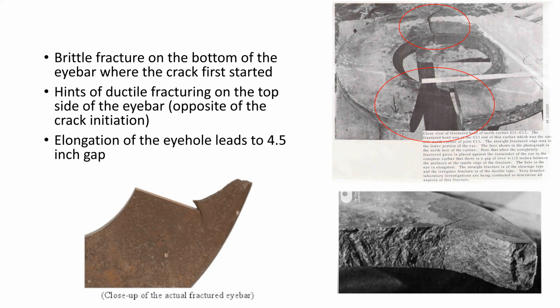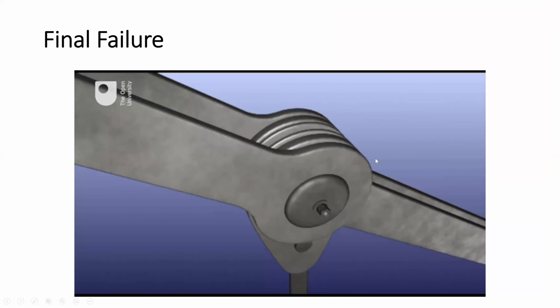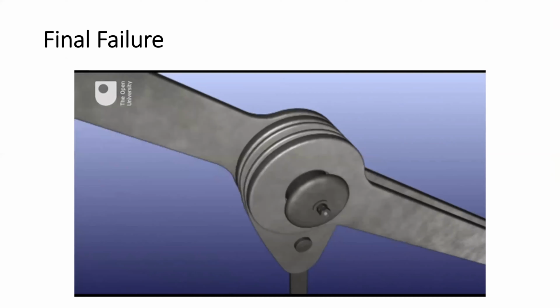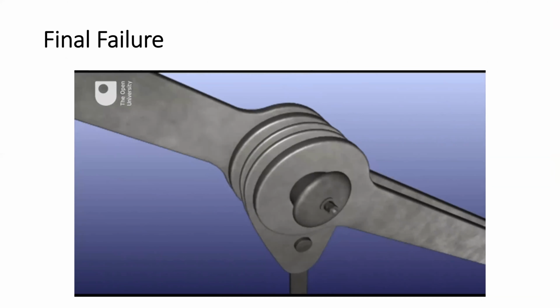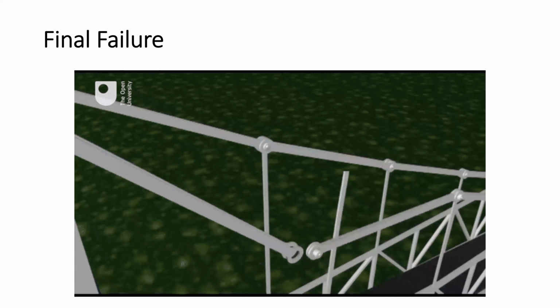The high strength, relatively high carbon content, and heat treatment of the eyebar steel results in a more acicular microstructure, giving the highest hardenability and strength, but very low ductility. Hence, this microstructure helped facilitate the brittle crack propagation of the eyebar up to the point where it started to fail. Once the eyebar failed, it caused a force imbalance that the bridge was not designed for. Hence, once one piece of the bridge broke, the whole bridge went into total failure and collapsed, as seen here.